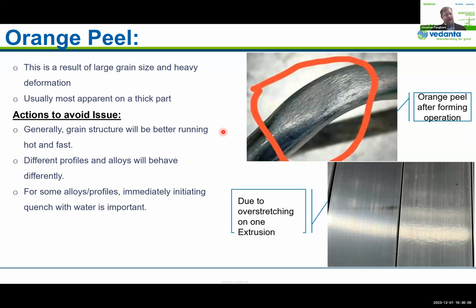And again, I said it before, but it's a consistent process, finding out what works and sticking with it, and really understanding not at a first order, but at the second and third order, making sure that there's consistency. For example, in this last point, quenching is important for some alloys, and really it's the time between extrusion and quenching that's important, which can be the most apparent problem if you have a delay at the press. So for example, the puller lets go of the part, you have to stop the press, or something similar happens. And then you have recently extruded hot metal sitting between your platen and your quench. Especially since it tends to be heavier shapes that have the problem to begin with. Often it's the water quench that is not happening, and it's being delayed for some time.